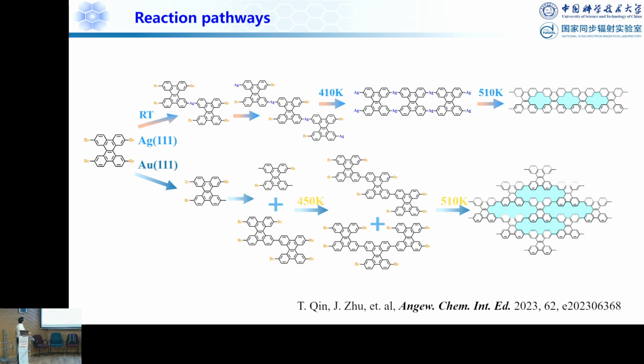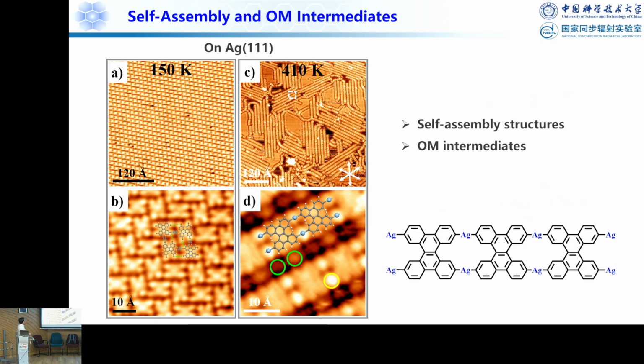The reaction happens through this organometallic intermediate. On gold 111, we form this two-dimensional graphene nanosheet, and there is no organometallic intermediate which we observed. Instead, they directly form the C-C bonds on the surface. So here is the STM result: at low temperatures when molecules stay intact, they self-assemble into a very ordered structure through the halogen bond and the hydrogen bond.